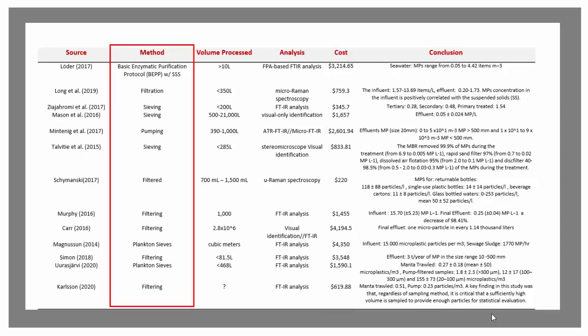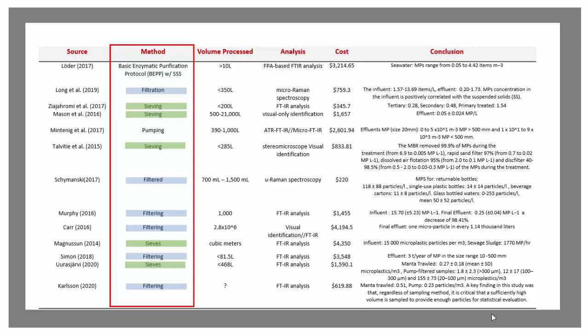So starting at the beginning with sample collection, you'll see that most sample collection techniques relied on two methodologies: either sieving of a sample, allowing you to get specific size fractions, or filtering a sample. I prefer sieving. Sieving, you can purchase sieves with different pore diameters, whereas filters tend to often clog and be problematic. And the sieves can be stacked from larger diameter down to smaller diameter, allowing you to collect specific fragments or particle size. And this may be very beneficial to some of these bottled water distributions in determining where in the process are the particles coming. Are they coming from the actual blow injection of the bottles? Are they coming from the screw-on lids? Or is there delamination of the polymeric membranes in the RO systems?